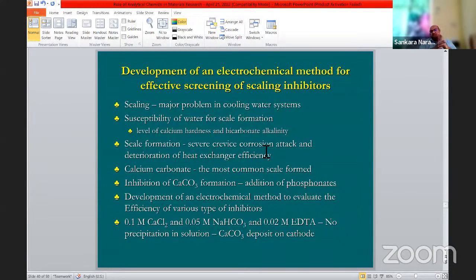Basically, we wanted to develop an electrochemical method. We took two electrodes. One is made the cathode and connected to the cathode terminal of a rectifier. The other is connected to the anode terminal, and we applied a potential of about 3 volts for about 1 hour. Automatically, calcium carbonate forms a precipitate on the cathode. There is a rise in pH at the cathode-solution interface, and that promotes the formation of calcium carbonate deposit on the cathode material.